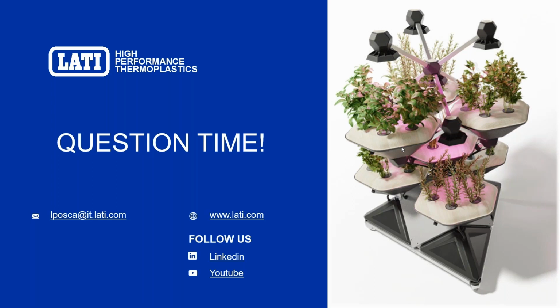3D printable thermally conductive? Yes, we have an experimental grade featuring ceramics for filament fused deposition. But if you are able to 3D print from granules, then the answer is yes, because thermally conductive plastics can be used as pellets for filament deposition from pellets, from granules. And the results are really very, very interesting, also from a thermal conductive performance point of view.